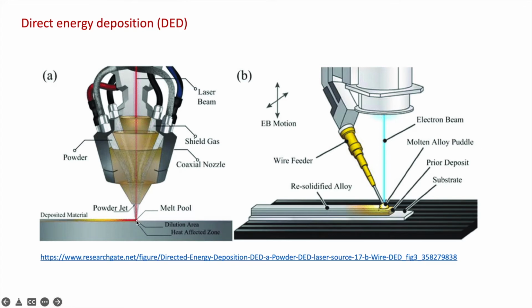After solidification, the printing head will repeat the process, printing the component layer by layer. Compared to the powder bed laser fusion technique you've seen in the previous slide, the powder jet DED has one major advantage. In this setup, you have multiple nozzles. Therefore, during the printing process, by changing the powder feeding rate, you can alter or tune the chemical composition of the printed components. Here, you can easily introduce a composition gradient in the printed component, which is not easily achievable using the laser powder bed fusion technique.